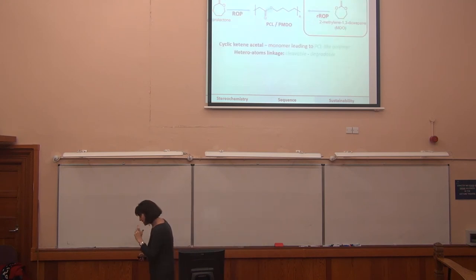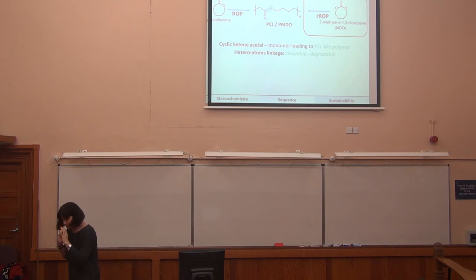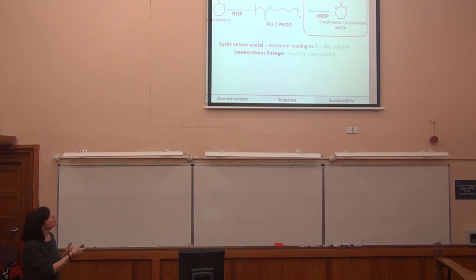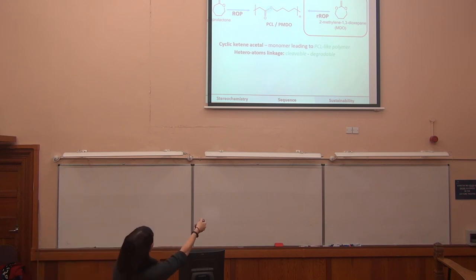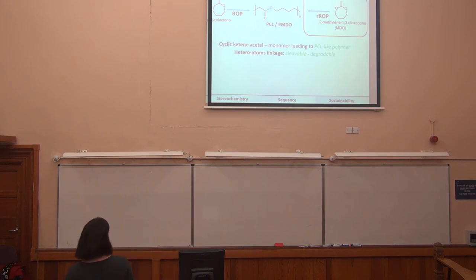The other thing that we've been quite interested in is we make lots of vinyl polymers with just carbon backbones, and they are really the problem in that they don't degrade. So the other program we have is this polycaprolactone, where if you do a ring opening, you form this polyester, which actually degrades, as I said, similar to polylactide over months rather than years. And we've been interested in this monomer here, this MDO type monomer, which has a vinyl and also these oxo groups, which are labile.